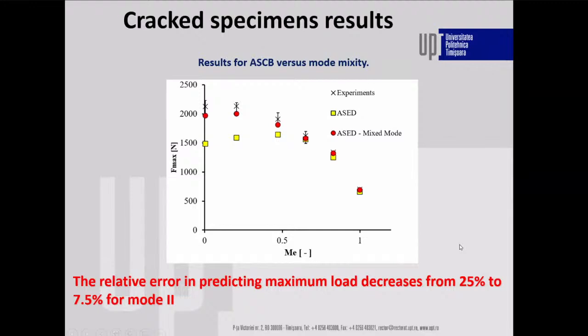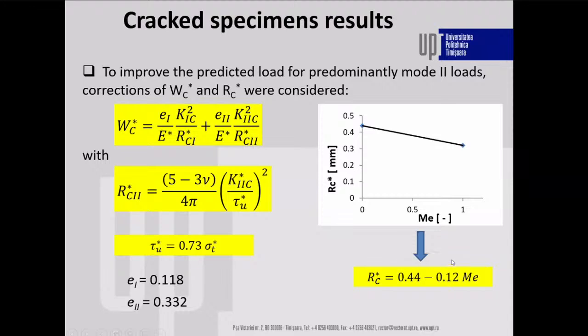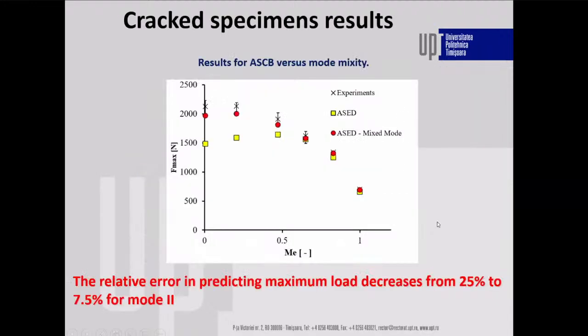So such a relation, and we recalculate our maximum loads, changing the control radius from pure mode 1 to pure mode 2. So having different values of the control radius. Obviously, the predictions go better, so the relative error in predicting the maximum load decreased from 25% in pure mode 2 to 7.5%.